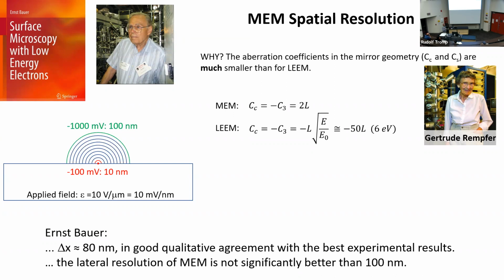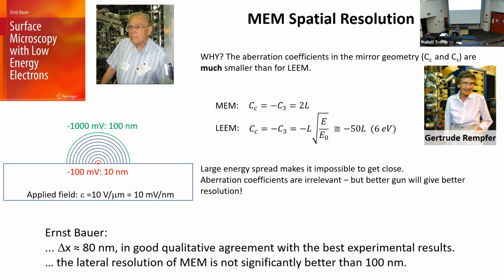The thing is, you don't actually image this object itself. You image the fields that the object creates in the vacuum, right? And they get bigger and bigger the further and further away you go. So the resolution is bad because we have always used bad electron guns, right? And if you use a better electron gun, you can get much better spatial resolution.